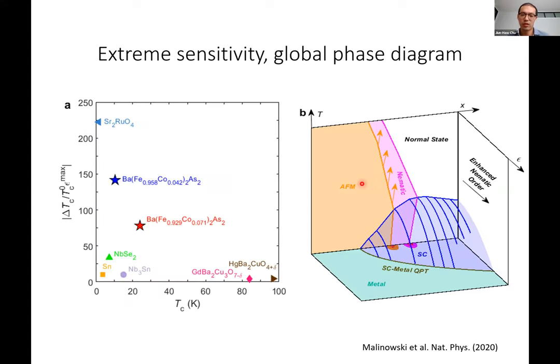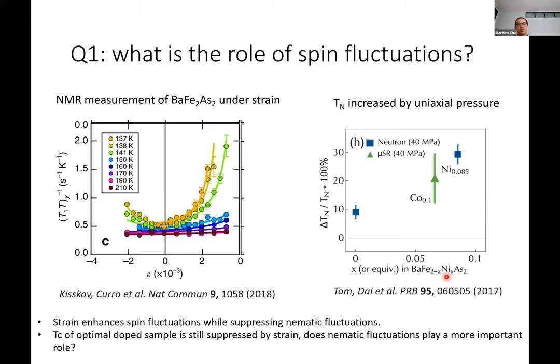We always have this antiferromagnetic phase in these materials, and spin fluctuation has been considered the leading candidate for the pairing of this material. And in fact, with strain, the TN increases. Here I'm citing one of Pengcheng's papers where you see the TN increase by pressure, and also from Nick Curro's NMR measurements as a function of strain, they also see that the spin susceptibility, the spin fluctuation, actually increases as a function of strain, both tensilely and compressively.